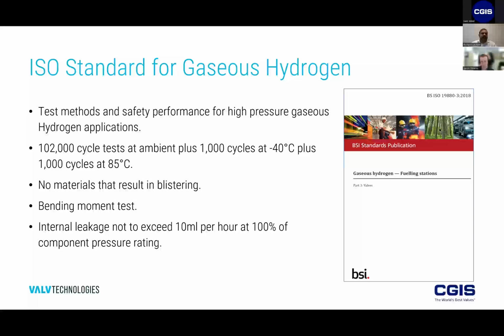And the way that it's split up is it talks about the different types of valves. So whether it's a check valve, a gate valve, a globe valve, or a ball valve, there are certain aspects that are relevant there. But having read through the document, I would say in general, it's a good start because we're really talking about specifically high pressure applications. Some of the requirements that it lays down is the 102,000 cycles. So basically, 100,000 cycles under ambient, and then an additional 1,000 cycles at minus 40 Celsius, so a cold test, and then an additional 1,000 cycles at 85 Celsius, which to a metal seated valve is really nothing. 85 Celsius is really not that hot.